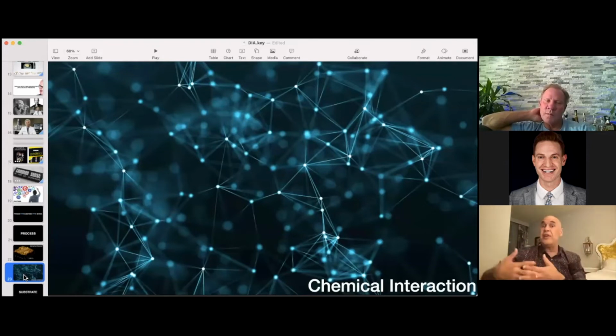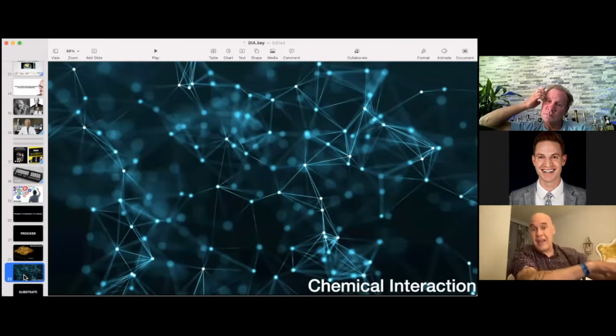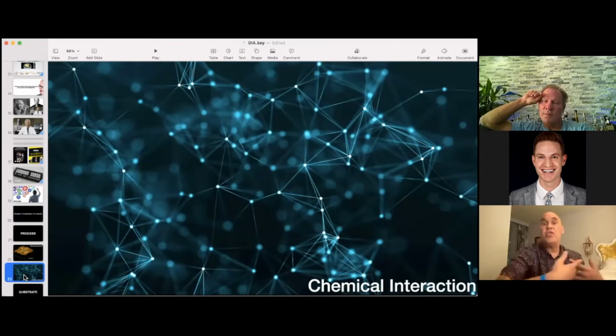Now, when you go to lithium disilicate, can you use a dental adhesive there? No. It's not going to generate chemical interaction. Whatever bond strength you're going to get is going to be generated by the mechanical retention you did when you etched. So you need to use something that is going to react with the lithium disilicate surface, such as silane, okay? Silane will do the trick.